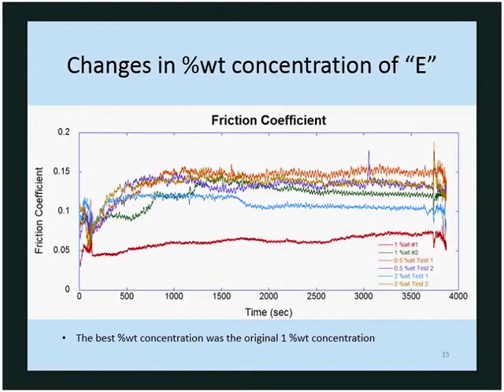And then changing the percent weight concentration of that particular oil that worked, changing it from 0.5 up to 2% weight in the oil, just to see if it had any effects, but the original 1% weight concentration was the one that worked best.